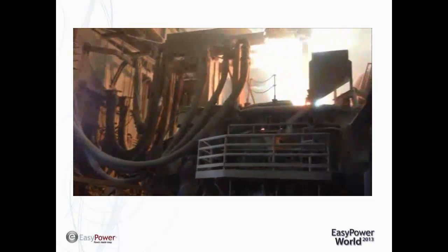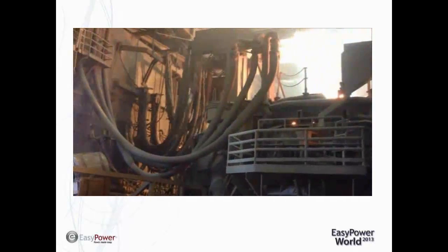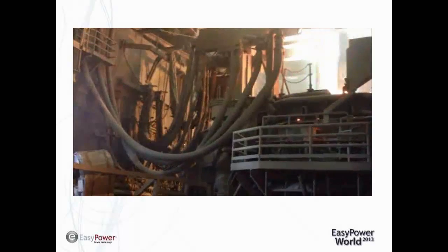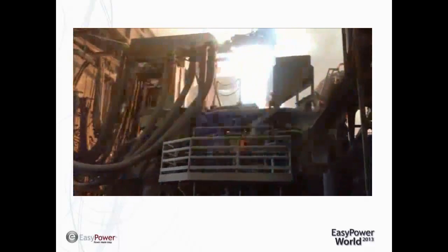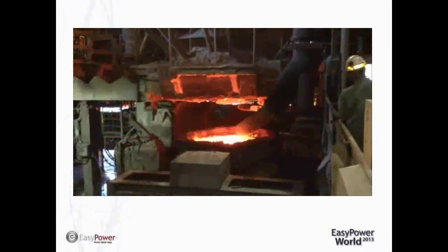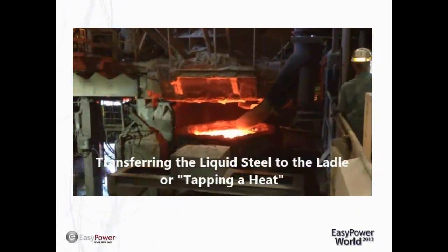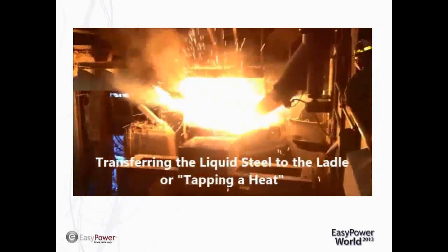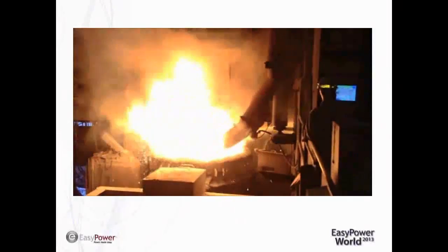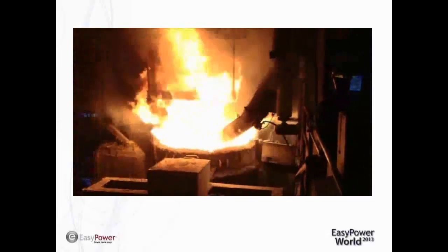And this is what we call bore-in, which is the most violent part of the heat. And again, this is about 50 to 52,000 amps to begin with, and by the end of the heat we'll ramp it up to probably somewhere around 62, 64,000 amps. Now you may wonder, okay, once the scrap is melted, how do we get it out of the furnace? Here you can see we've got a refractory lined ladle positioned under the furnace, and once we get to somewhere between 2930 and 3000 degrees, we'll actually move the molten steel from the melting vessel into the ladle, and this is called tapping a heat.